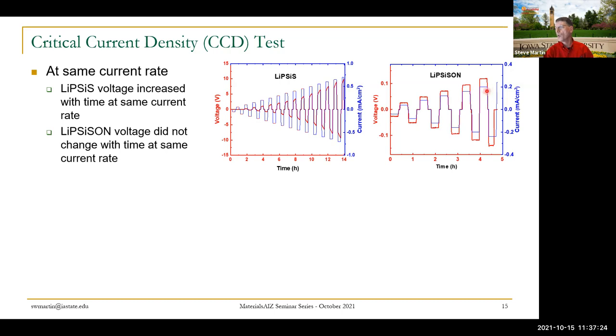But yet look at the currents. They're on the order of 0.5, 0.2. They're a little lower, but not that much lower. And you can see now the perfect ohmic behavior. We drive this square current with a square voltage. So you can see at this range, the glass is acting ohmic. It means that the glass is chemically stable at the interface. We apply a voltage and yep, the ions move across the glass